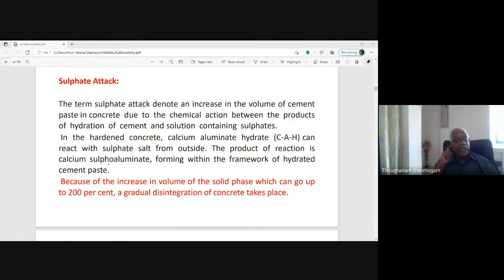In the hardened concrete, calcium aluminate hydrate gel can react with sulfate salt from outside. The product of this reaction is calcium sulfoaluminate, forming within the framework of hydrated cement paste. Because of the increase in volume of the solid phase, which can go up to 200%, gradual disintegration of the concrete takes place.